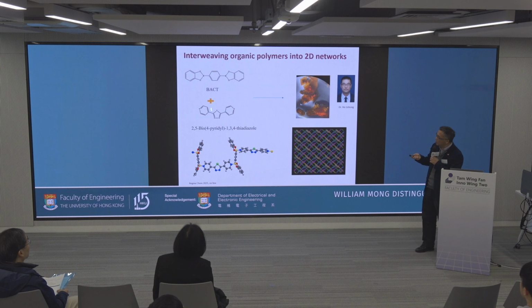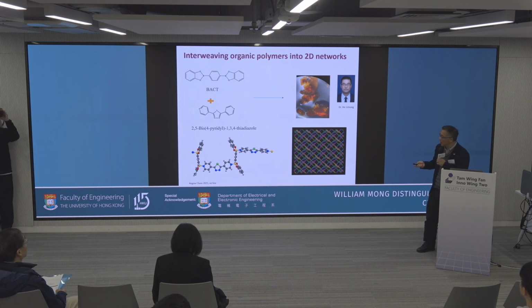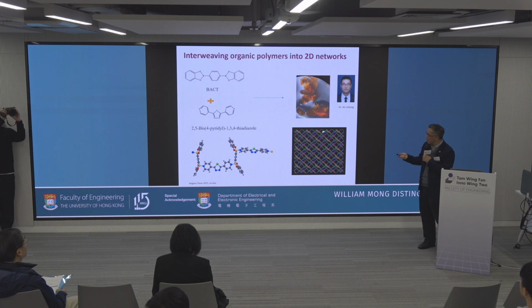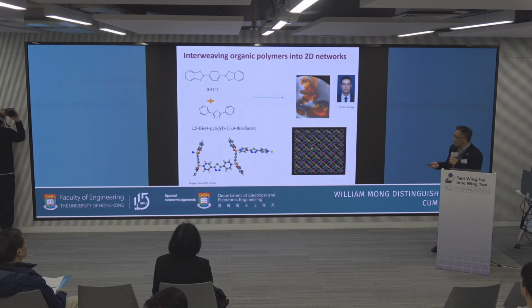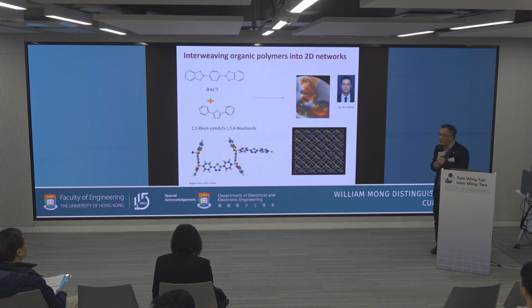We try to have more coordination with the polymer chain, so that's why we use the sulfur and then 2 nitrogen here. When we got this crystal structure, and he solved the crystal, we found that these 2 nitrogen can coordinate with the boron centers, and they can form the polymer chain. During the crystal growth, this polymer chain can intertwine with each other and form the 2-dimensional structure. And these 2-dimensional structures intertwine together. Then we can use this nanosheet to protect our lithium metal. So this actually has good application for the lithium metal battery to protect the metal.